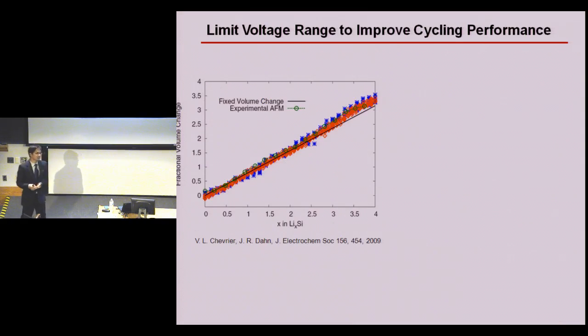So of course, we want to solve this problem. We get a very nice structure, we get very high capacity, but we get very bad cycling performance. So how to solve this problem? This is a simulation study about the volume change versus the number of lithium you put inside the silicon. Of course, the volume change will be proportional to the number of lithium you put in. So how about we decrease the number of lithium we put inside the silicon so that we still get high enough capacity, but the volume change is not that high so that we can still get stable cycling performance?